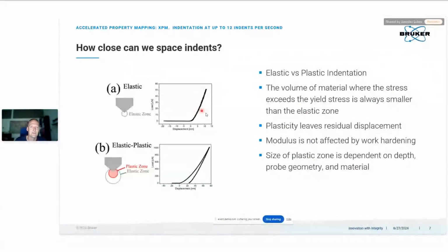In this way, you can measure elastic modulus, but in the case of hardness, you have to go over the yield strength of your material. You have to produce a plastic deformation. Otherwise, the hardness value that you measure is not really reaching the intrinsic property of your material. So you need to produce a plastic deformation zone together with the elastic zone. The elastic zone is always bigger than the plastic zone; the plastic zone is smaller. That also means that if you have different phases around, the hardness value is less affected, or more local. So you measure the hardness in a more local way.